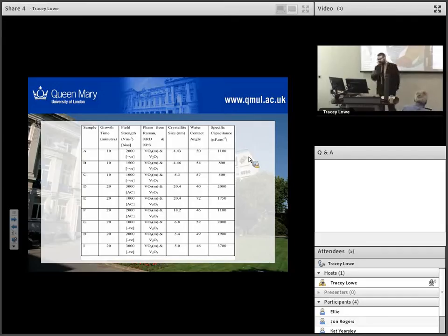So close to 4,000 microfarads per square centimetre. I guess you probably don't work in this area, so to give an example, the best carbon-based materials are around 400-500 microfarads per square centimetre. For ruthenium oxide, it would probably be nearer 8,000, but actually this is pretty good considering the cost, so we were quite happy with that.